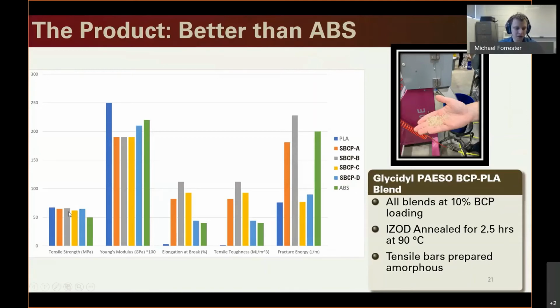I'm going to focus on this gray curve, the dark blue curve, and the green curve. This is PLA, our block copolymer, and ABS. And what we see is that by incorporation of this block copolymer, we have almost no change in tensile modulus, or tensile strength. In fact, we see an increase compared to ABS.